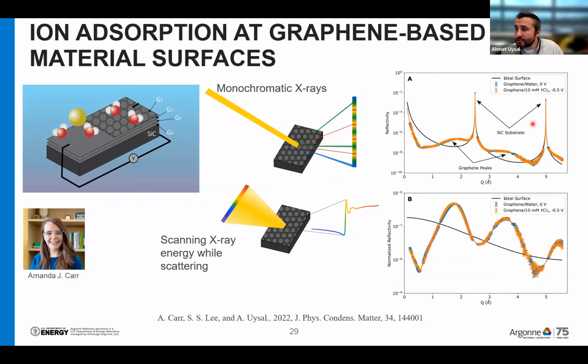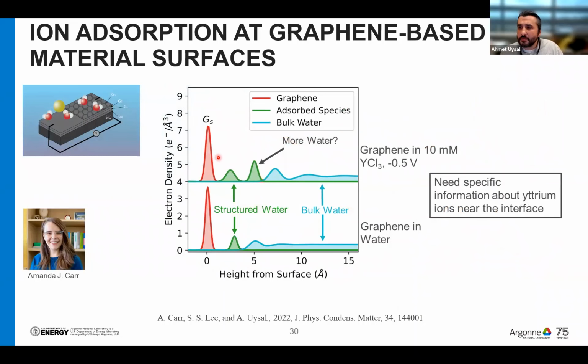Now, our crystal truncation rod measurements show some differences, and when we fit this data, what we see is we can get the electron density profile at the interface. Here is our graphene, and this is the water. We show different colors because this is just graphene in water, and then this is 10 millimolar yttrium chloride, and we are applying a negative potential to the surface. Now, we see some structured water at the interface.